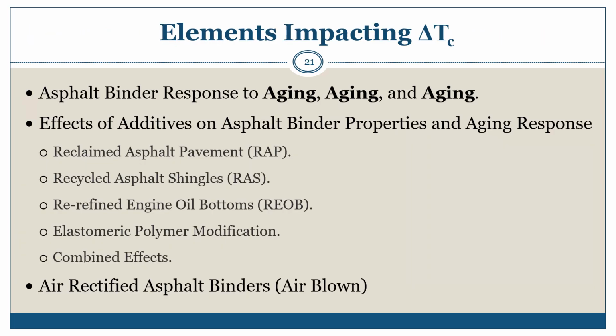From what has been presented, we can see that one of the more critical elements impacting the delta Tc of asphalt binder is aging. Like extended aging of virgin asphalt binder, combining pre-aged materials such as RAP or RAS with a virgin asphalt binder could result in an asphalt binder with a more negative delta Tc. Re-refined engine oil bottoms, REOB, vacuum tower asphalt extenders, VTAE, and other fluxing agents for softening and adjusting low temperature parameters of asphalt binders are also known to impact delta Tc.